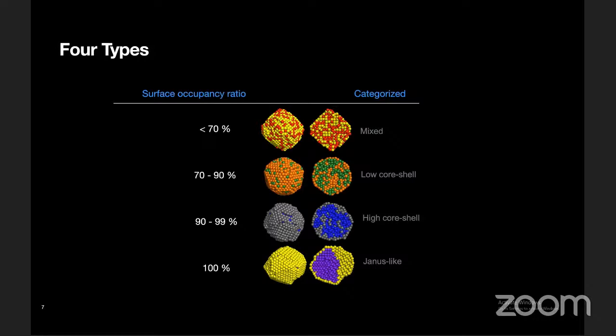And once we've done the analysis for the MD result of each combination, we made our own criteria to categorize the structures. For example, when neither of the materials occupies more than 70% of the surface, we label them as a combination that prefers a mixed structure. On the other hand, if one of the materials occupies more than 90% of the surface, it is labeled as a high level of core shell structure. So based on these criteria, each combination was categorized as either mixed, low level of core shell, high level of core shell, or Janus-like.